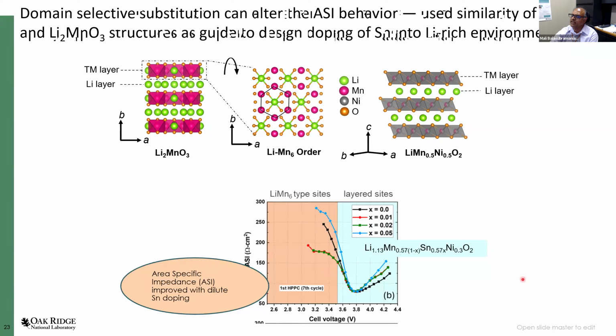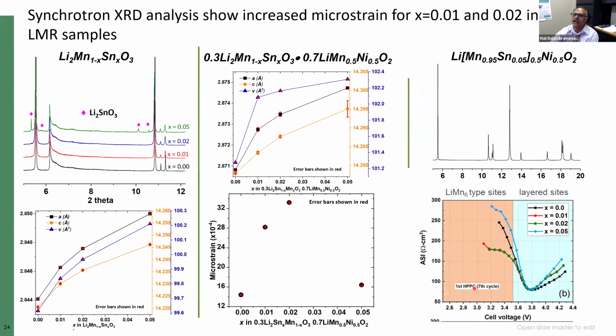So having come up with this idea, we wanted to show that we can actually understand the tin site selectivity in this material. And so we performed synchrotron XRD. This work was done by Subhadip Malik, who's a postdoc at Argonne. One of the important takeaways that he found is that for small, early amounts of tin doping, the tin seems to substitute in the lattice. But when we start going to higher amounts of tin, particularly for this composition, Li2SnO3 starts precipitating out. So we want to try to maintain it at these low concentrations.